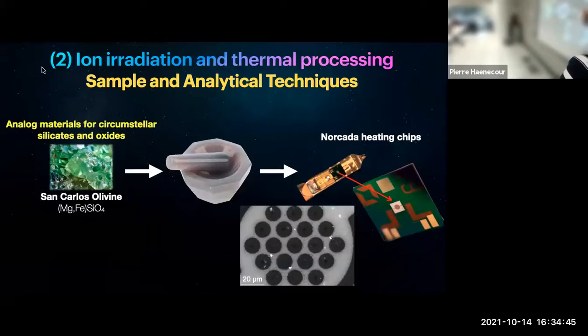Okay, so now I wanted to switch to the second type of experiment that we've been doing. We're trying to not just look at thermal metamorphism by just heating, but combine it with ion irradiation. What we did in this case, instead of using a meteorite to try to constrain it even better, is just use standard material. So here we just used silicate, San Carlos olivine. You must all be familiar with San Carlos olivine. Very similar to what we would expect, for example, for a presolar silicate. Olivine is a very typical presolar silicate.